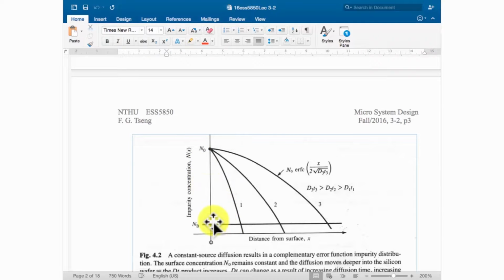And as time advances, you can see the profile. This is the profile of the impurity inside the silicon wafer, from zero deep into your silicon substrate. At the start, you can see the profile is quite steep. And as time progresses, you can see the impurity goes further into the depth of the silicon substrate. So as time goes on, more and more area has been diffused by the impurity. This function is an error function type.